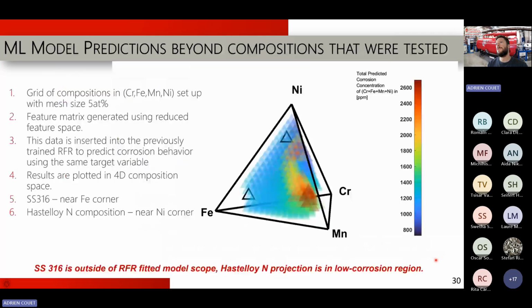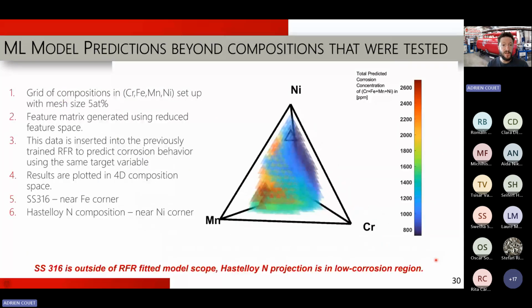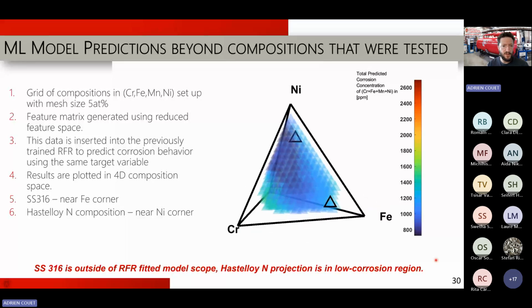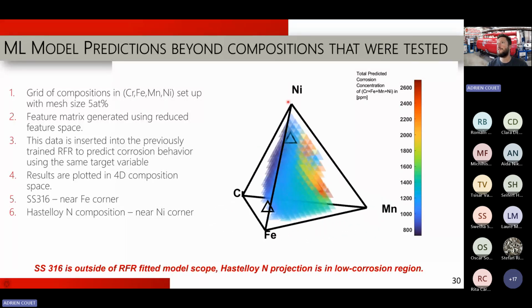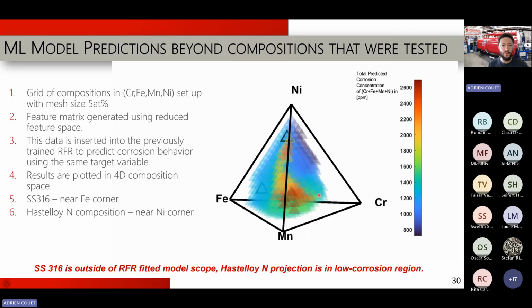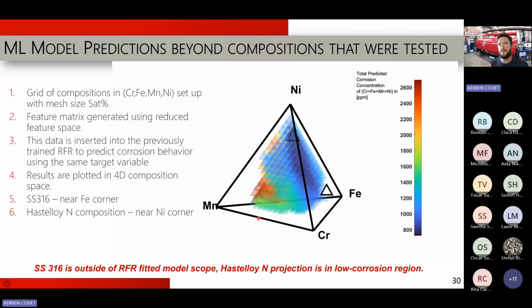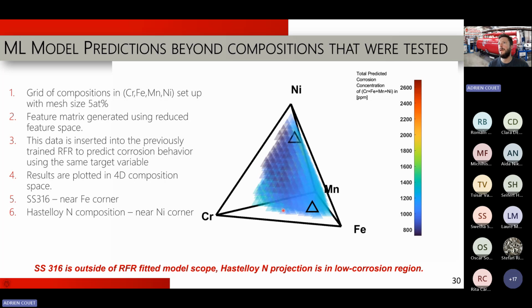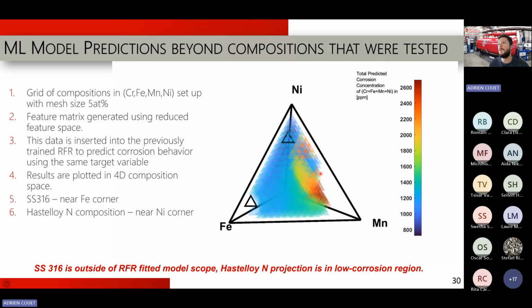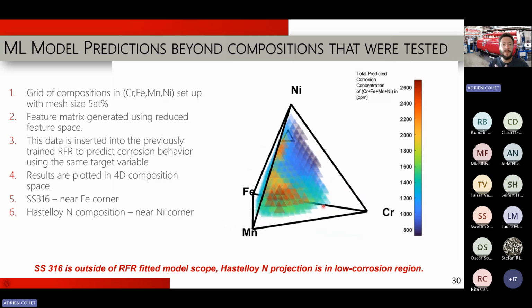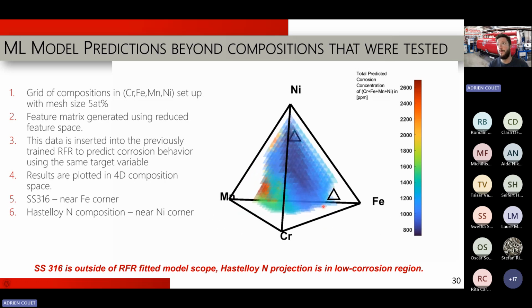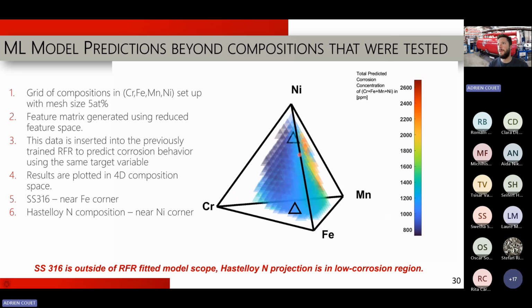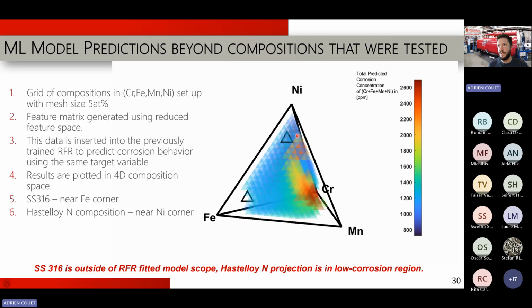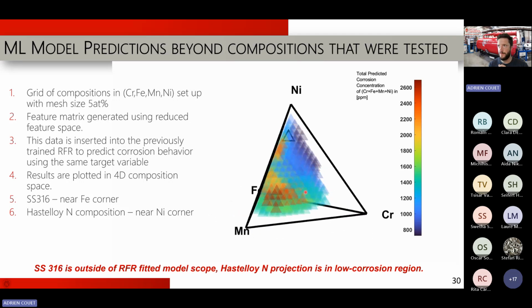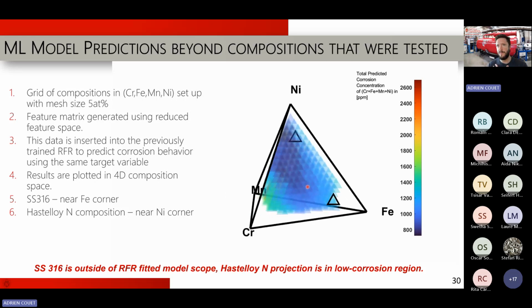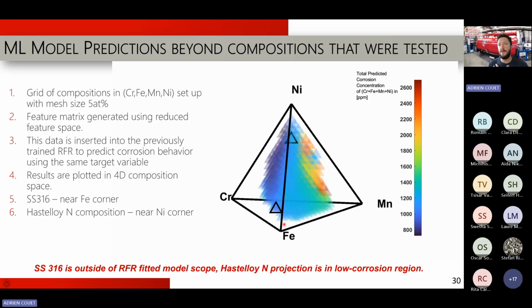I'll pass on this one here, but now you can actually use the machine learning algorithm to predict corrosion of alloys that you have not tested. So here is a corrosion magnitude, in terms of corrosion products in the salt, that the random forest regressor is predicting. And not surprisingly, but that's a good thing, you see the higher manganese and the higher chromium tends to corrode more, or is predicted to be corroded more. And on top here, you see Hastelloy N, which is a nickel-based alloy that has been developed for molten salt. It's a projection of Hastelloy N, because there is more than just those 4 elements. And then stainless steel 316 is down there.